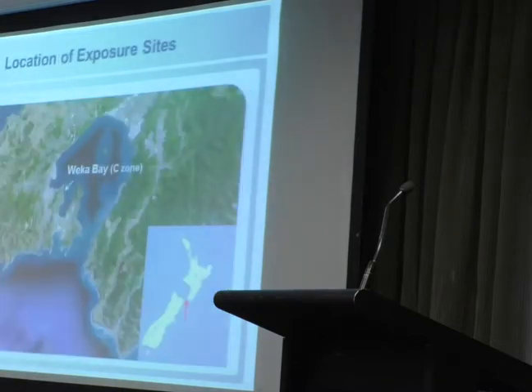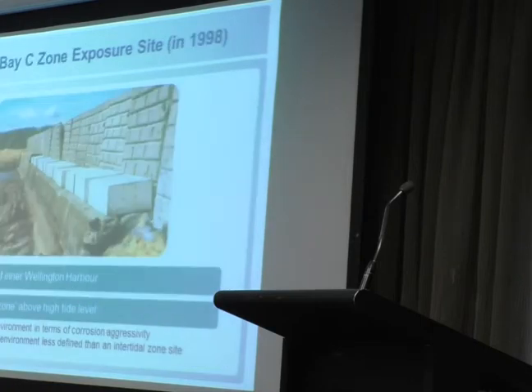And I'll just talk about the two sites that pertain to marine concrete exposure. So what's called in our code the C zone, which is environments where the concrete may be subject to direct splashing or wave action, so typically within 100 metres of the high tide, and the coastal perimeter zone, which is sort of 100 to 500 metres from the high tide zone, depending on which way the wind is blowing. Both those exposure sites are located in Wellington, which is on the bottom of the North Island there, indicated by the arrow. This is the C zone exposure site.